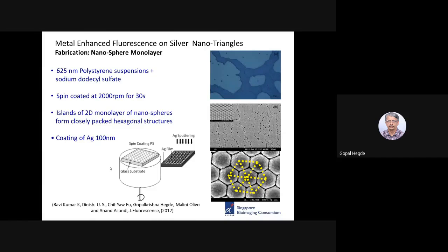You know that in biology, the first thing for any measurement is they go with a microscope, then with fluorescence. Some of the biomaterials are not highly fluorescent. If the fluorescence is below a certain level, then you cannot measure. So one thing they want is fluorescence enhancement. That's what we started with. Is it possible to enhance the fluorescence using the plasmonic effect? Is it possible to make nanostructures, then put the weakly fluorescent biological material on this nanostructure and enhance the fluorescence? That's how the problem started, and we are able to make such nanostructures, silver nano triangles, silver planar.